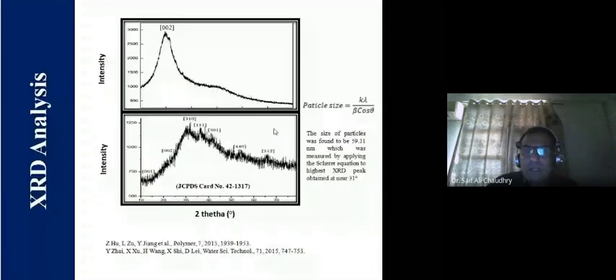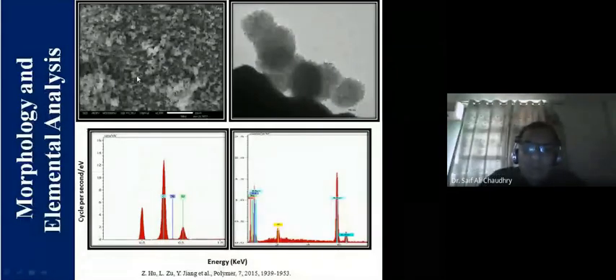Now XRD was used to find the size. The Scherrer formula was used to find the size of the particle, which came to 59.11 nanometers. That indicates the size of the particle. Right? SEM, scanning electron microscopy, was used to study the morphology or the surface structure, and then TEM, transmission electron microscopy, was used to measure the size of the particles.